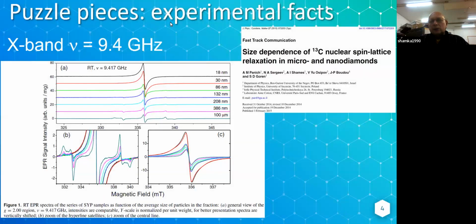First publication, puzzle pieces, experimental facts. The first experimental publication of a more or less careful study, let's say, because I am one of the authors of this article, I cannot say careful, of what really happens when you change the size of the diamond particle, was published in the beginning of 2015. And here you can see changes in spectra.